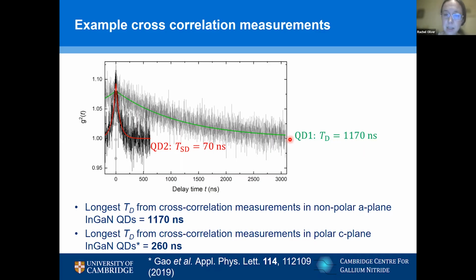What's quite exciting, though, is just how long our longest spectral diffusion timescales are, because if we can optimize our growth to make that the norm in these samples, that's a really pretty impressive number. For comparison, the longest timescale of spectral diffusion from cross-correlation measurements seen on polar C-plane indium gallium nitride dots is about 260 nanoseconds. And these numbers of a few hundred nanoseconds are actually quite similar to what's seen in the arsenides.